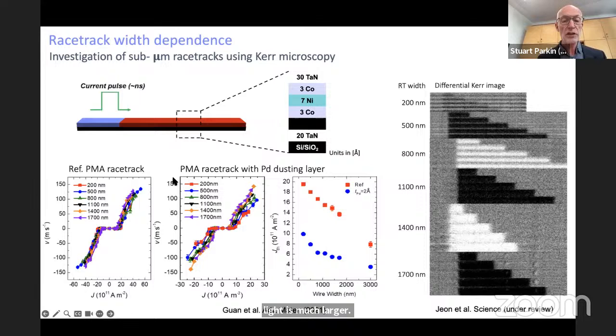This is the velocity of the domain walls shown in the 2 leftmost pictures as a function of the current density within nanosecond long current pulses. And you can see essentially the velocity versus the current density is pretty much unchanged as we change the width considerably from 1700 to 200 nanometers.